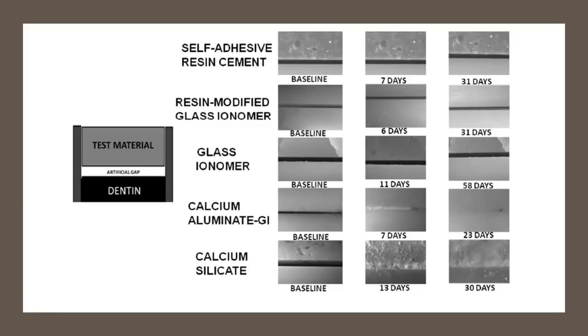Let's take a closer look. So they evaluated a self-adhesive resin cement, and at 31 days it still had an open margin. A resin-modified glass ionomer still had an open margin. Glass ionomer, an open margin. And then there was a calcium aluminate, which was Ceramir, and a calcium silicate, which was actually MTA.